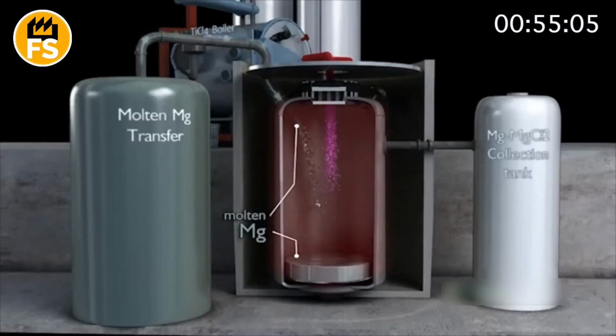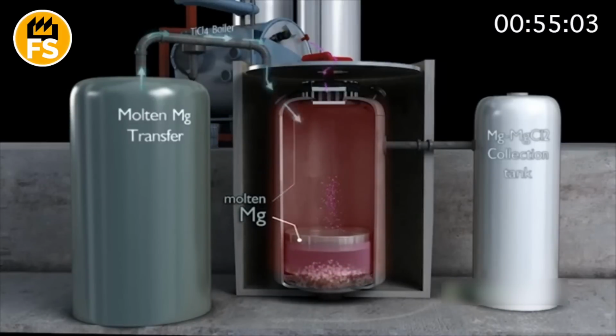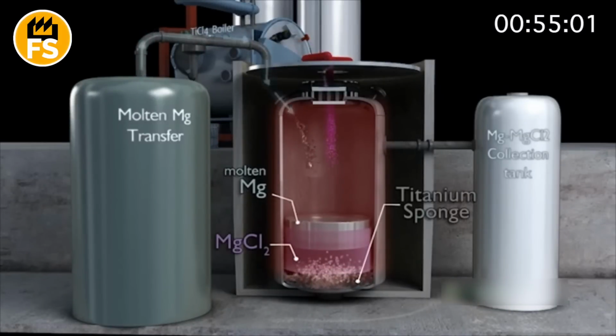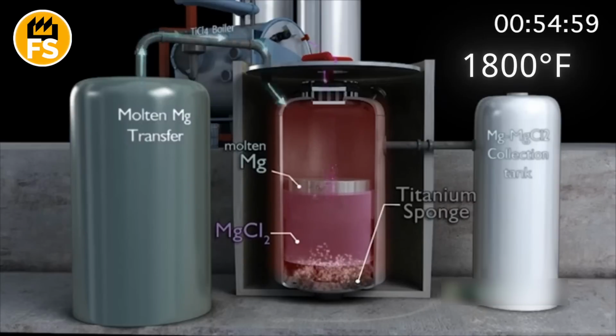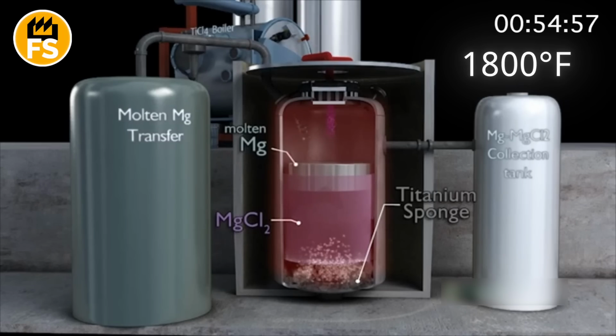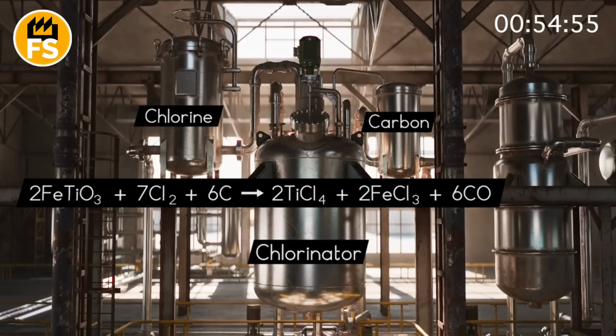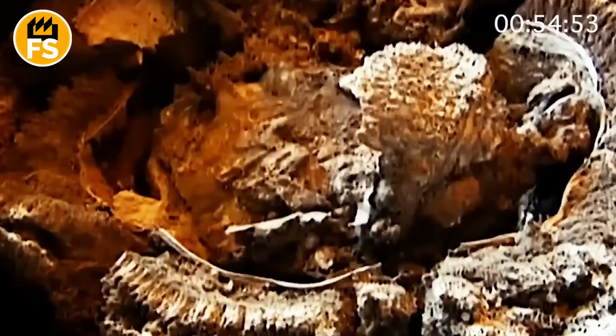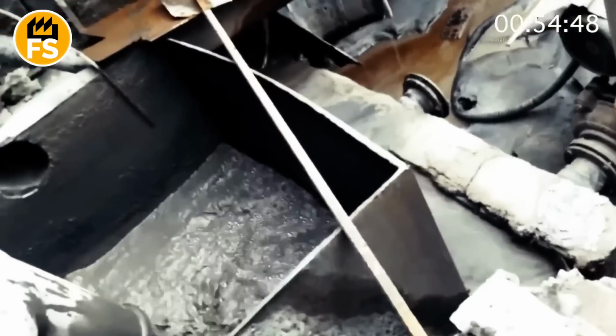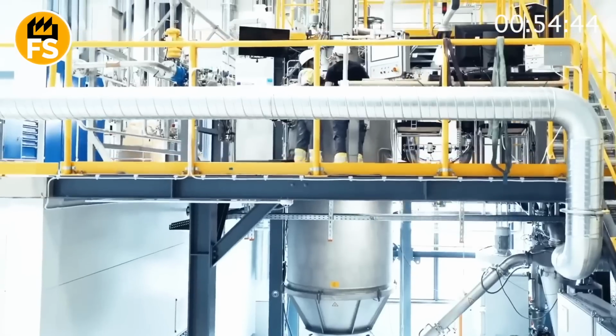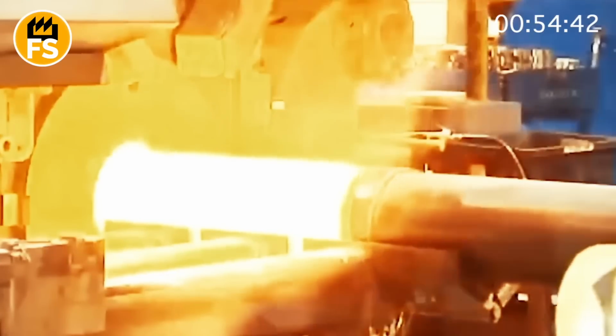For this, concentrates of titanium ores are subjected to chlorination in fluidized bed reactors at a temperature of 1,800 degrees Fahrenheit, where carbon and gaseous chlorine react with the raw material, forming titanium tetrachloride and carbon monoxide. This tetrachloride contains impurities of other metals, which are removed by distillation, obtaining high-purity technical titanium tetrachloride.